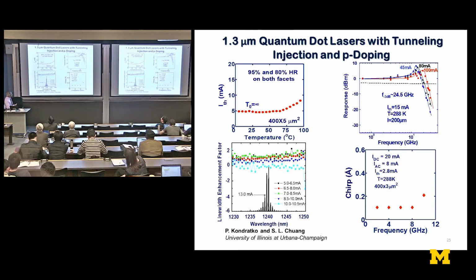Line width enhancement factor and chirp, these are two properties that indirectly tell you that your differential gain is very high. See, when you're injecting carriers, you're modulating the refractive index of the gain region. And this gives rise to chirp. So the lasing wavelength keeps dancing around, and the line width also broadens.